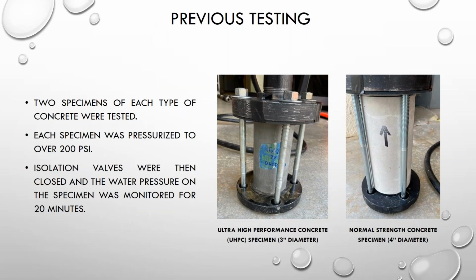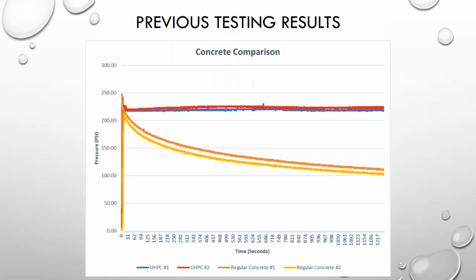Previous testing, we tested 2 types of concrete. One is the UHPC, you see over here on the left, and also regular concrete. Both specimens were pressurized at 200 psi, and then the isolation valves were closed, and that left the specimens pressurized with the 200 psi water, and then we monitored how the pressure dropped over 20 minutes. And the results, you can see the red and the blue line over here are the UHPC, while the brown and the gold color are the regular concrete. As you can see, there's about 100 psi drop with the regular concrete, while there was very little drop at the UHPC.